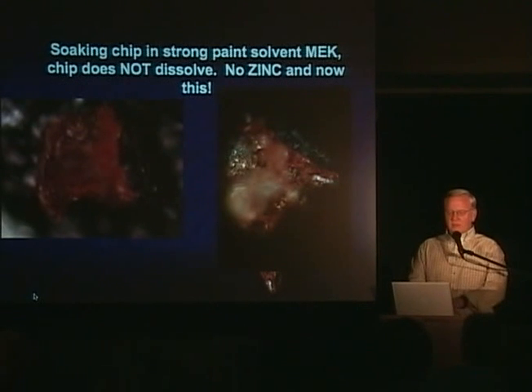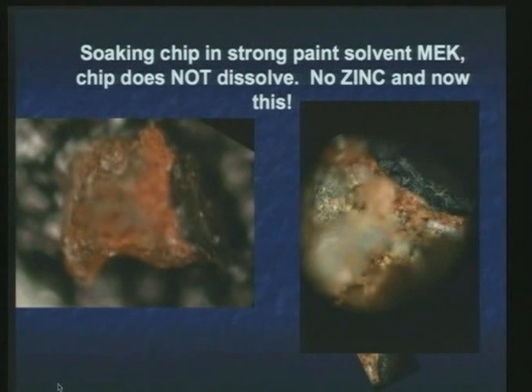Instead, what you see in these photographs is that the red portion swelled. The gray-black portion did not seem to be affected by the solvent at all. The red portion swelled, and can you see in the right photo the porosity that's now evident in the chip, the red material? This is primarily silicon dioxide, silica, with some iron oxide mixed in. And in the left-hand side of the right photo, you see a silvery region. We found that the elemental aluminum separated out under the action of this paint solvent. Very interesting. Remember, there's a lot of carbon in here. The carbon does seem to break down.